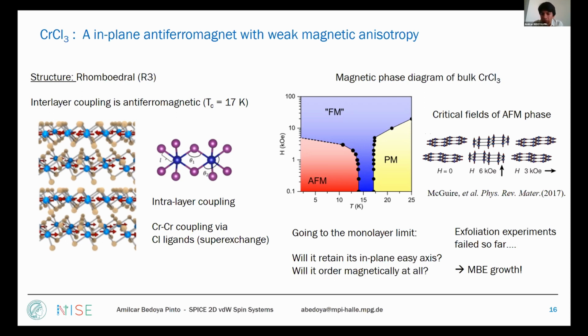So far, we have also been looking at the literature, but all the exfoliation experiments failed so far to prepare a true monolayer chromium chloride, presumably due to degradation issues in the monolayer regime, probably that are more critical than in chromium iodide, because in chromium iodide it is possible. So there were no reports of any tunnel device experiments whatsoever. So we decided to start the MBE growth of this material.